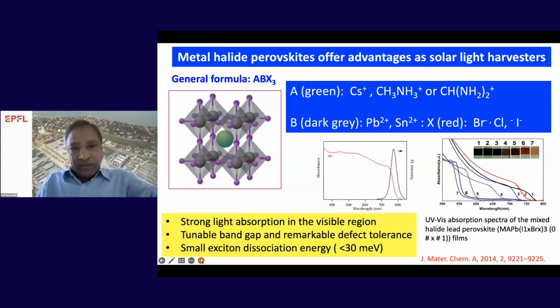So what is perovskite actually? The perovskite material is a simple composition containing ABX3. A is a cation. This cation can be inorganic like cesium, or organic like methyl ammonium or formamidinium. So those are the A cations as shown here in this perovskite structure. The A cation occupies the vacancy of the cavity. And the B is a metal cation, which is lead 2 plus, tin 2 plus, but in our presentation, I will be mostly focusing on lead 2 plus metal. And X is a halide, the bromide, chloride, and iodide. So these are the halides.